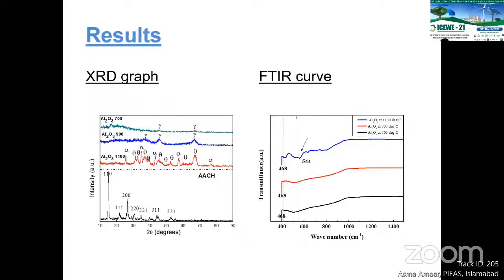Next are the results. This XRD graph is showing that after drying, we got AACH, ammonium aluminum carbonate hydroxide, and the XRD peaks are confirming that it is AACH. And when this AACH was calcined at different temperatures, at a lower temperature only gamma alumina was produced, but at higher temperature crystalline phases were produced like alpha and theta alumina.